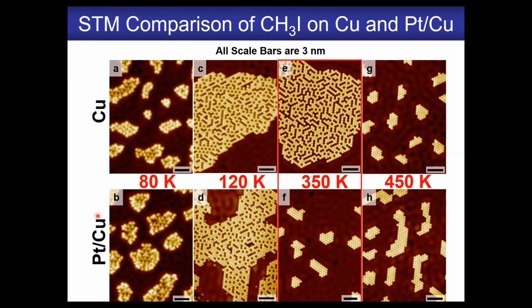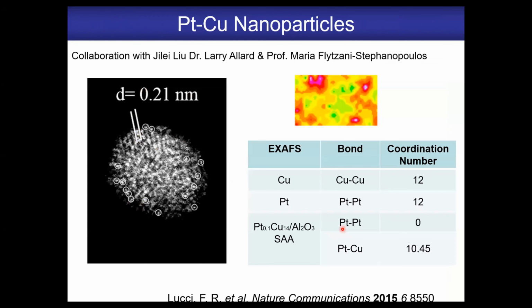But you can see clearly here that when you have just 1% platinum atoms in the surface, your reaction's finished by 350 Kelvin. All you've got left over is the iodine atoms that came from the methyl iodide. So that's demonstrating that you can do very clean chemistry where methyl goes to ethene, propene, and methane just by adding 1% platinum to the surface. And you see we start with a half a monolayer coverage of reactants, and just 1% platinum does the job because these intermediates will diffuse around the surface, find a platinum atom, CH activate, CC couple, and give us our coupled products. So again, go in to test that to see if it works under industrial conditions.